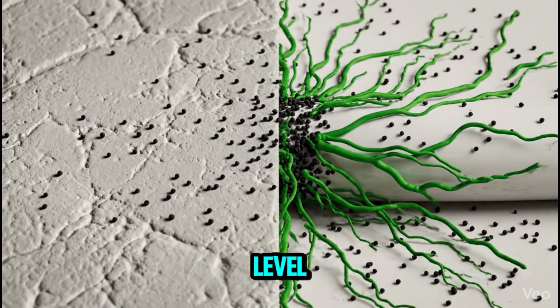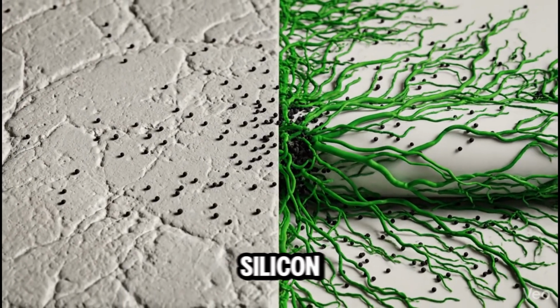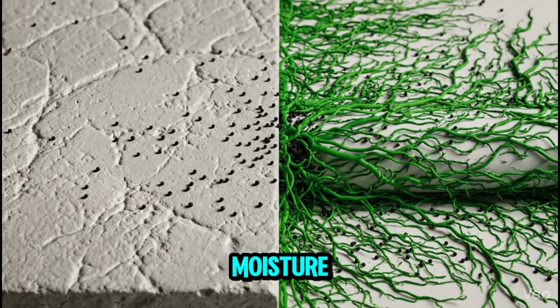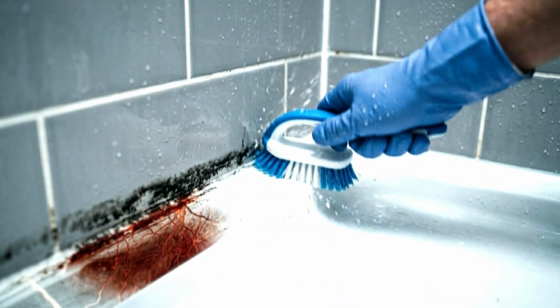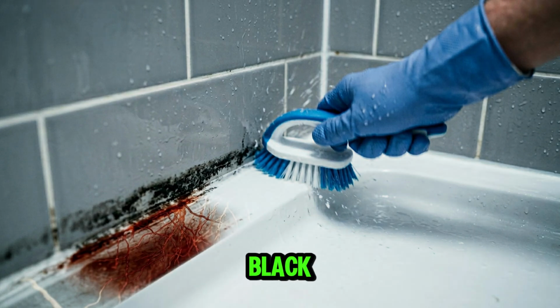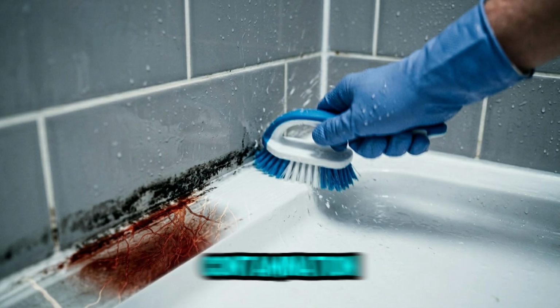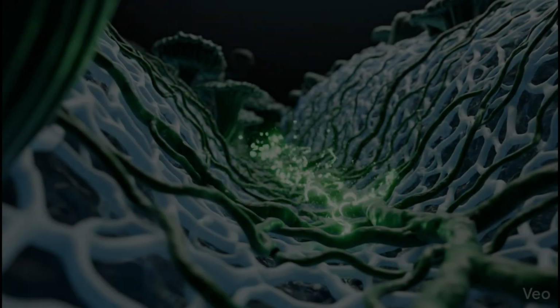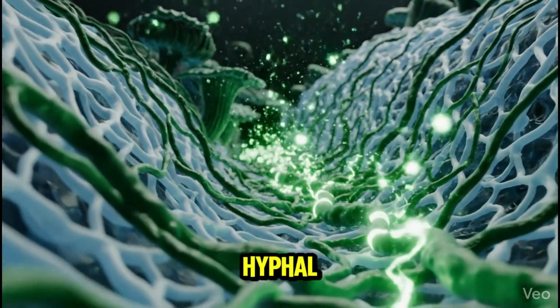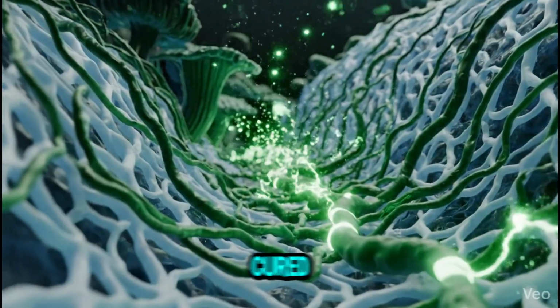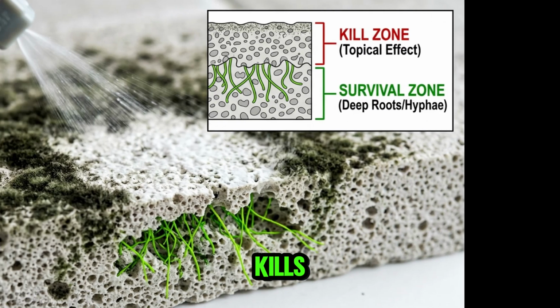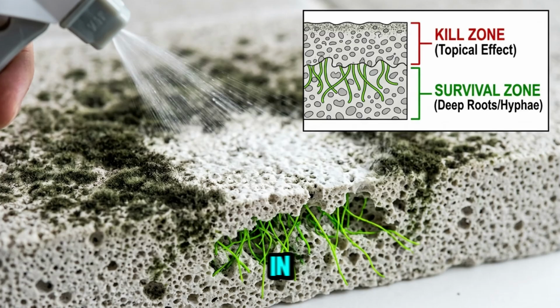On most surfaces, without adequate moisture at the microscopic level, they do not germinate. On silicone joints in bathrooms, where the moisture interface conditions are consistently favorable, they do. This is why the black you see on silicone joints is not surface contamination that can be cleaned off permanently. It is an established colony with hyphal penetration into the surface microcavities of the cured silicone. Bleach kills the surface expression, but the hyphal network in the microcavities survives or reseeds quickly from ambient spores. Within weeks to months, the colony reestablishes.